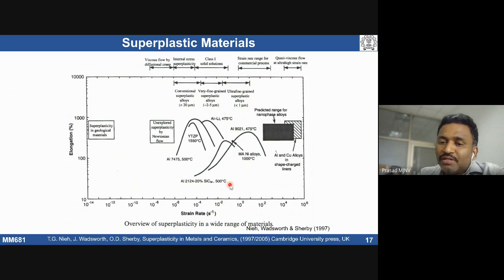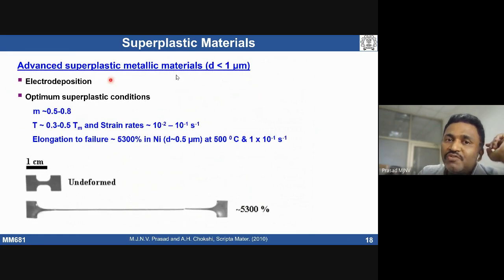This was demonstrated, I think, during my PhD. We took a material, nickel, by electrodeposition, with a alloying element, sulfur, added. It was shown that the material can show very large elongations, around 5,000%, at a strain rate of 10 power minus 1 per second, even at a lower temperature, 500 degrees Celsius, around 0.3 to 0.5 times the melting point. The grain size at that temperature is about 0.5 micrometers, 500 nanometers.